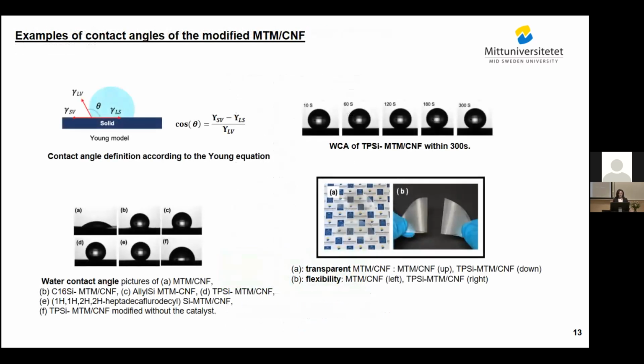The contact angle is the parameter that gives us information about the surface wettability. And Young has a definition of contact angle based on the interfacial energy of the whole system when the liquid has contact with the solid. Here I bring examples of the contact angle: in picture A, we see MTM-CNF without modification, and picture F shows us the MTM-CNF modification, but without catalyst.